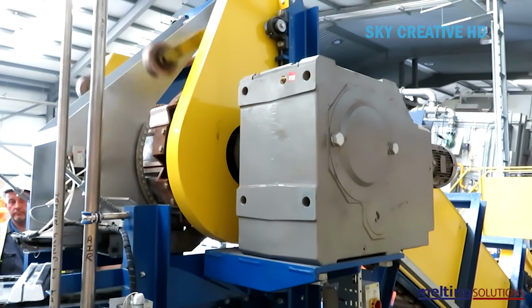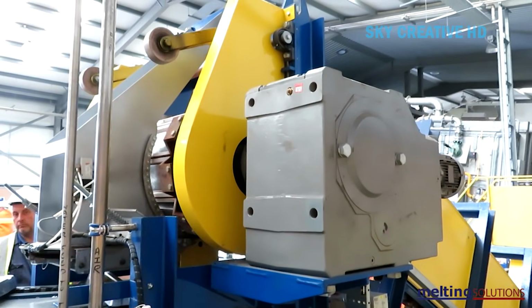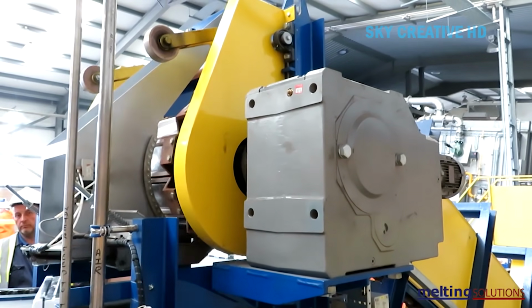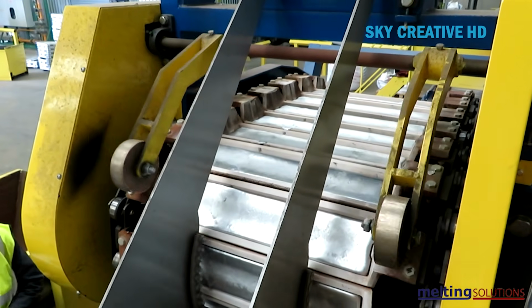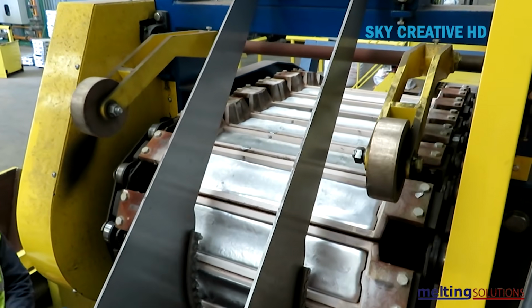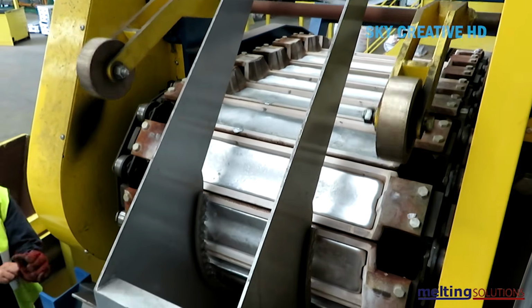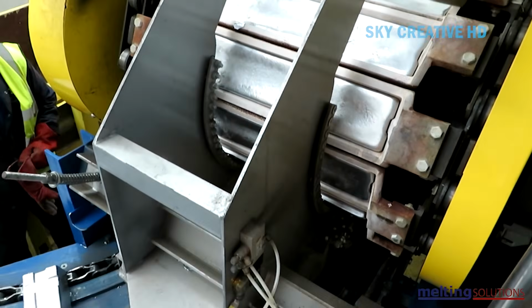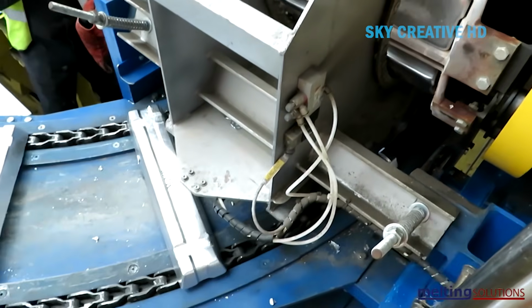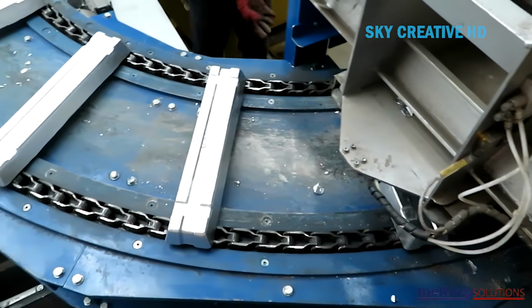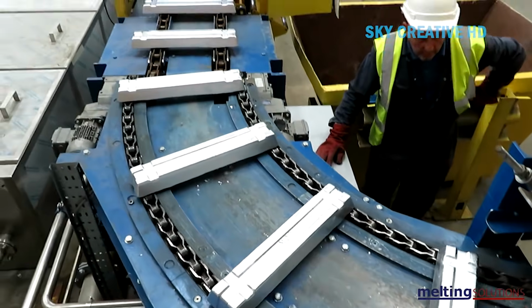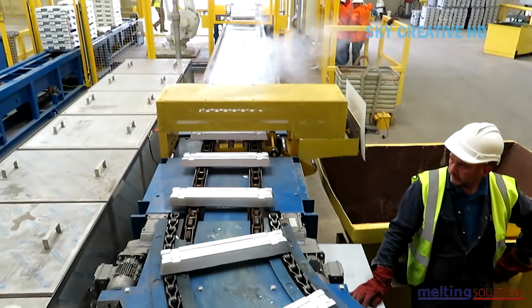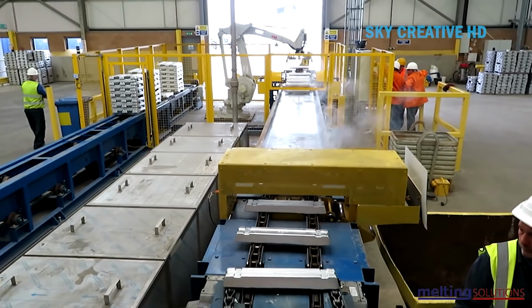This controlled cooling rate is important because it determines the grain structure of the solidified metal, which in turn affects the mechanical properties of the finished ingot. Too fast, and you can introduce internal stress. Too slow, and you lose production throughput. The 220 mold configuration gives this plant impressive production capacity while maintaining tight metallurgical control.